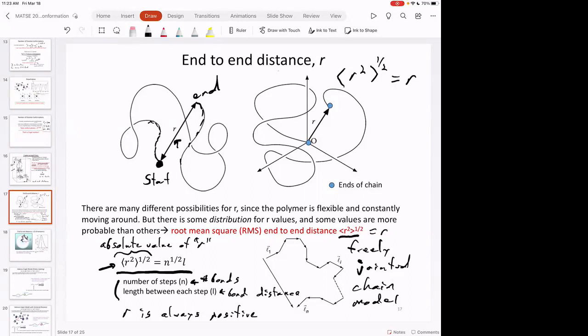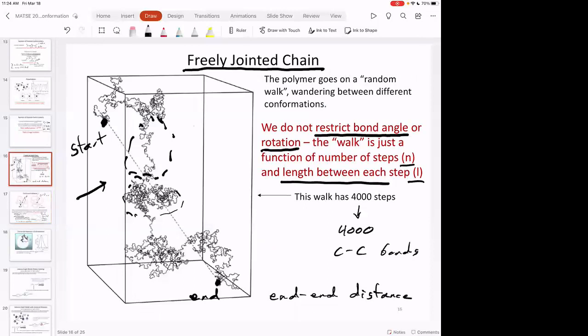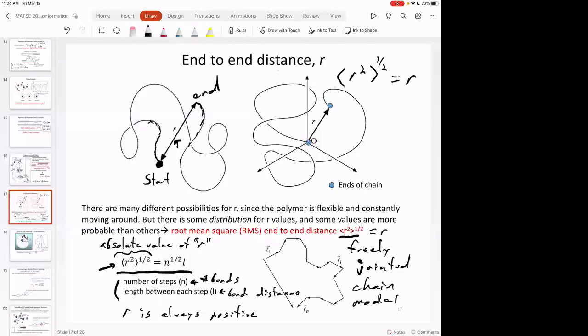And so, you know, it doesn't matter what distance we calculate. N is unitless, right? Because that just tells you the steps. That's the number of bonds, same as always. But in this case, we use 1.54 because we're taking steps per bond. What's the carbon-carbon bond length? And so we use the bond length in this equation. We don't use anything else. So the fully extended chain is special because we need to figure out what that shortcut distance is, but not in a lot of these examples, because we can think about taking a step, and all those steps are where the carbons lie on the backbone. Okay, great. So we have a really simple way to calculate the end-to-end distance of a model polymer.